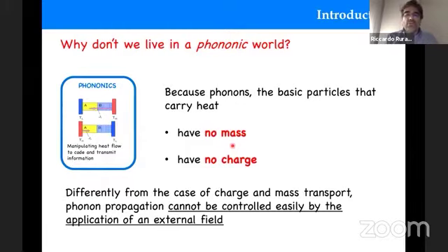However, what I would like to do in today's talk is to challenge this statement and show you that indeed you can use, for instance, an electric field to do that. Of course, it is true that the phonon as a quasi-particle has no mass and no net charge. So if you think in a very simplistic way of a phonon like a quasi-particle traveling in space, it is true that you cannot use an electric field to slow it down or to accelerate it. But phonons are collective vibrations of the lattice. So if your lattice is polar, you can affect the lattice, and then in turn it would affect the propagation of the phonons.